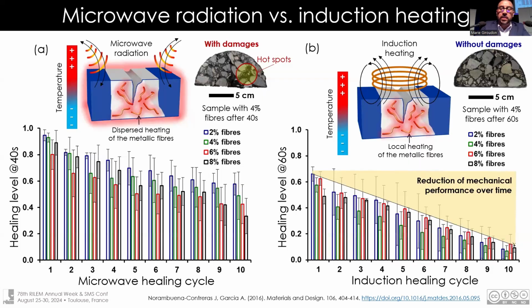Comparing both heating technologies has shown that microwaves can achieve a higher healing index over time, but they can also affect the microstructure of the asphalt mixture. For example, you can produce hot spots when you expose the material to high temperature. The recommendation is to use induction heating in on-site conditions without affecting the asphalt mixture performance.